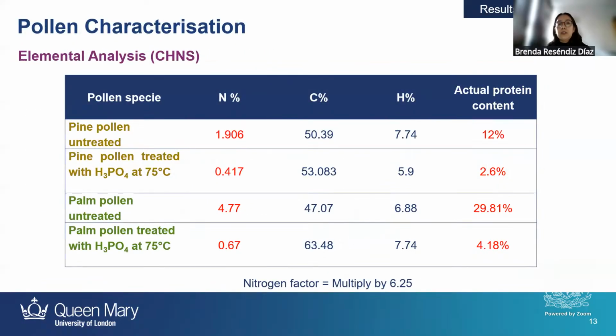Also, it was important to know the nitrogen percentage. The nitrogen percentage will give you an estimation of the protein content in the pollen structures. So here are the percentages of nitrogen, carbon, hydrogen from the untreated and treated pollens. We can observe here that when it was untreated, we have 12%, and after the treatment, it was 2.6%.